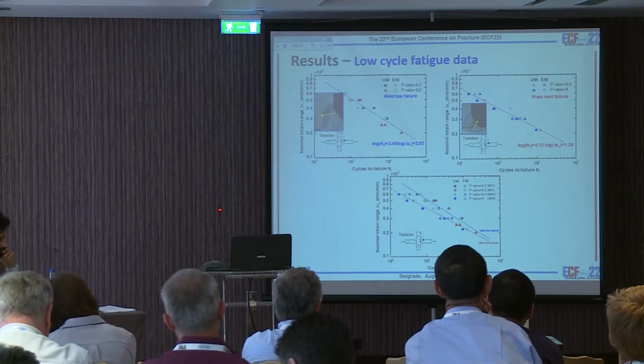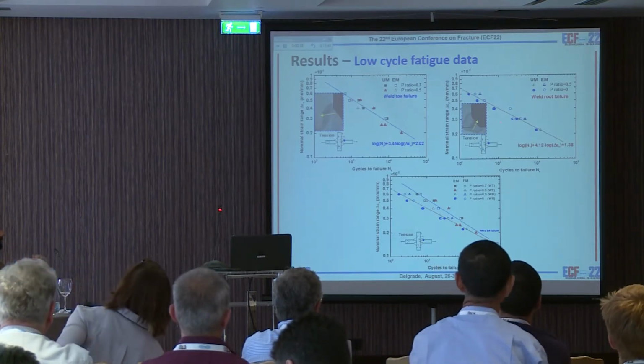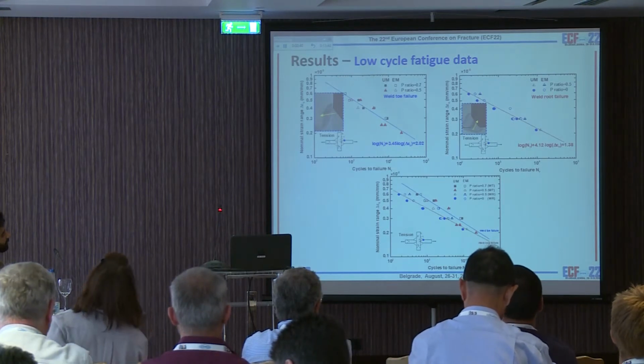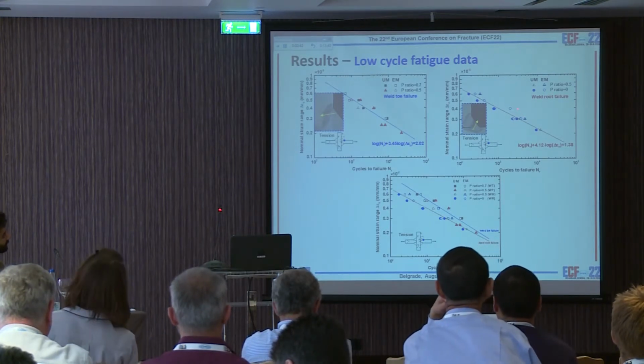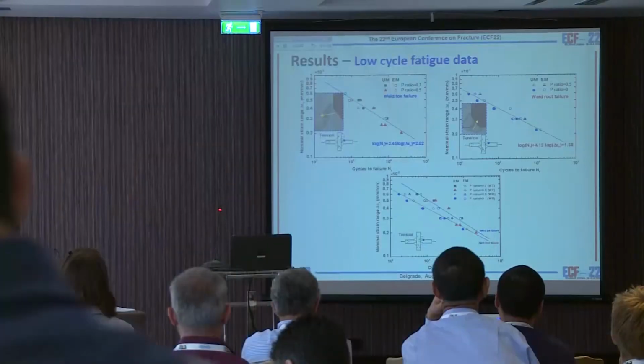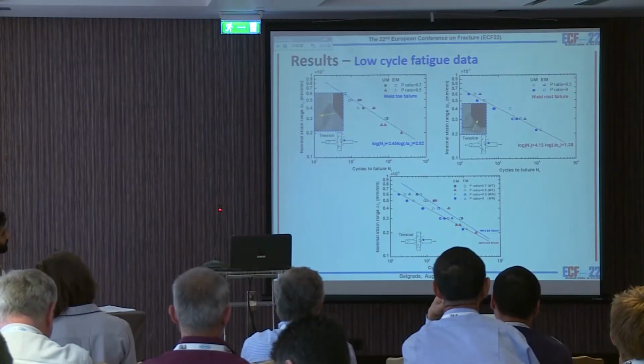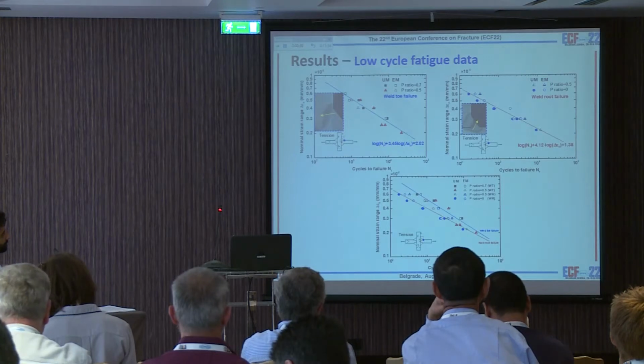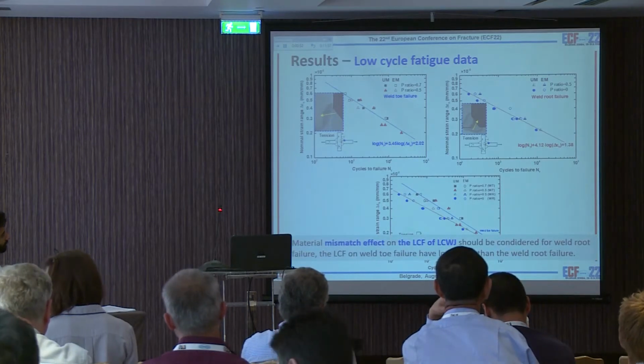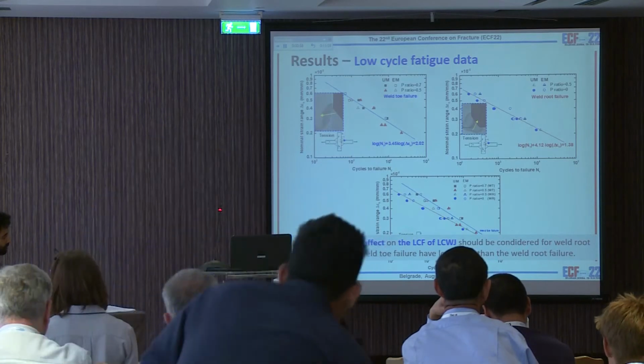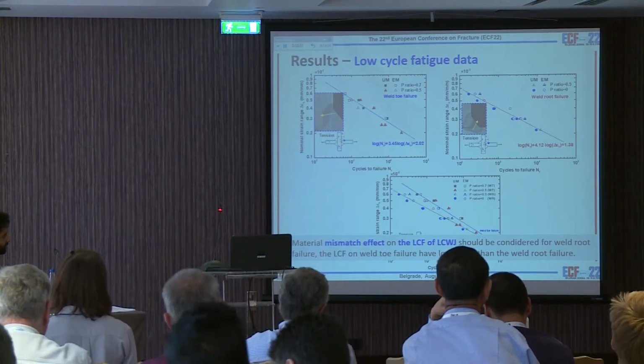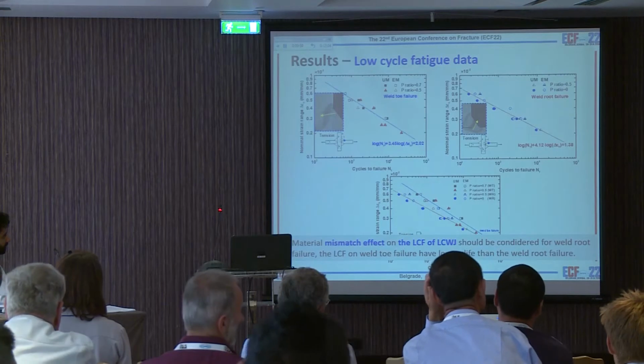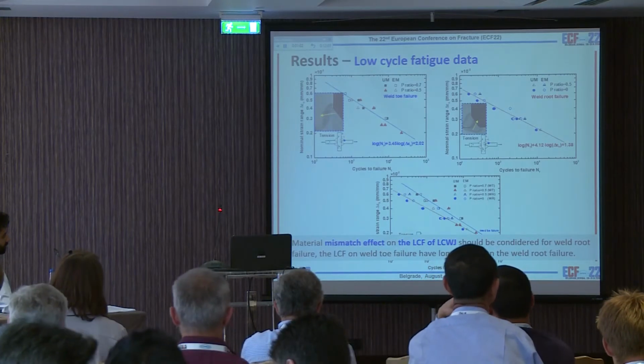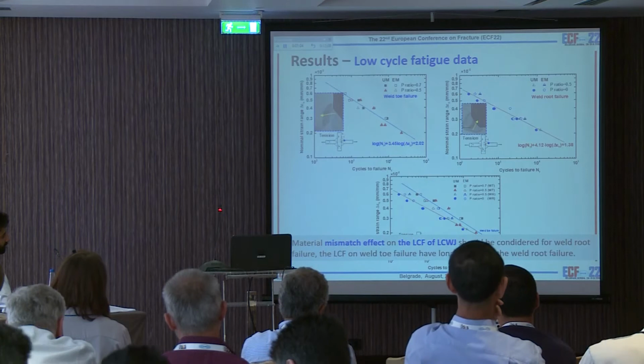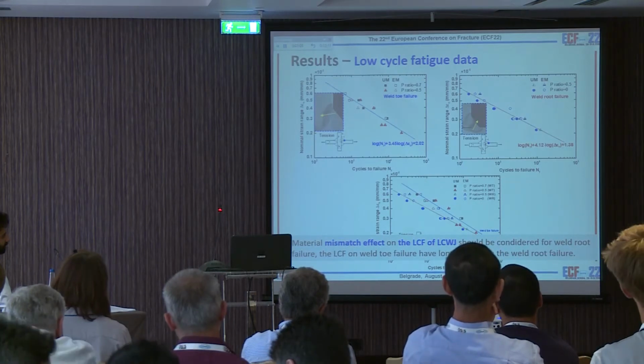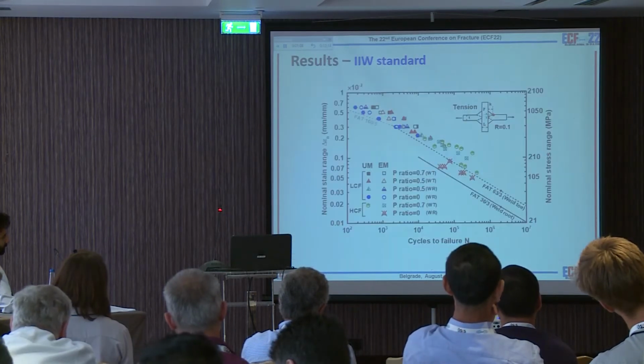We find that the welded root failure is lower than the welded toe failure. But we can see in this picture for the welded root failure, the mismatch shows some effect between the undermatched welded joint and the even matched welded joint. So we can find the mismatch effect on the low cycle fatigue of LCWJ should be considered for welded root failure, and the LCWJ on the welded toe failure has a longer life than the welded root failure.